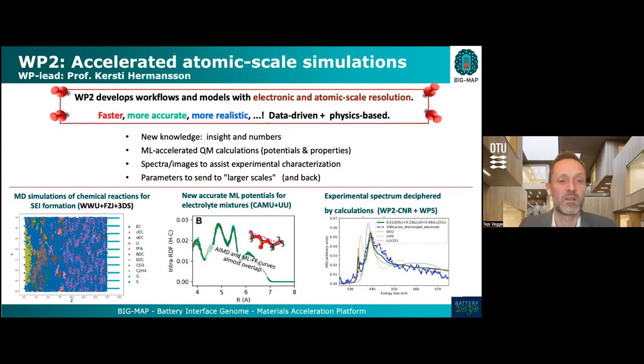This is some of the work at Cambridge, where they are able now to account for these variations in inter and intramolecular forces, such that we have almost the same radial distribution functions as we would have with traditional and much, much slower potentials. It's also the work package where we can provide experimental validation of chemical or electrochemical spectra that are obtained, mapping out which species account for the experimentally observed spectroscopic fingerprints, and deduce the composition of species. This is work done at CNR.